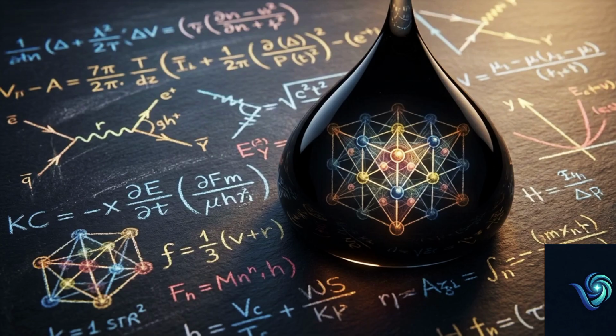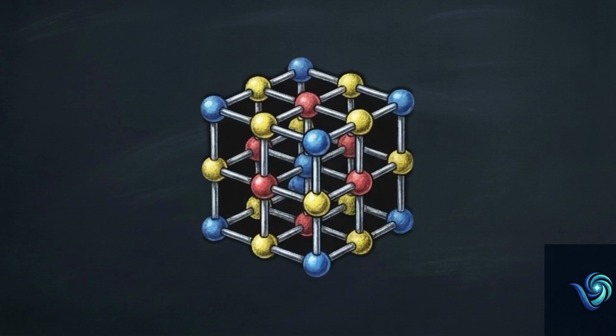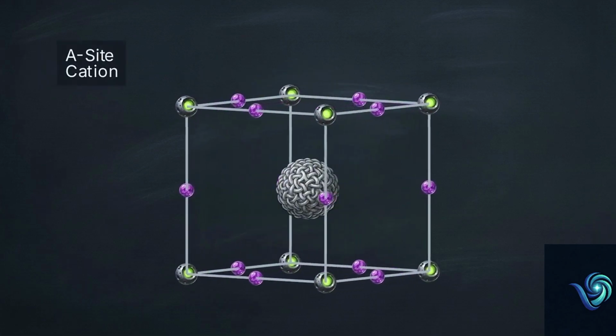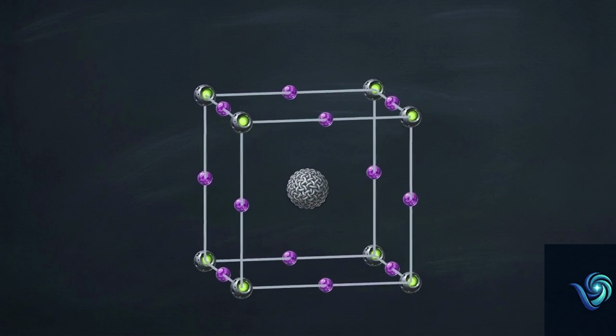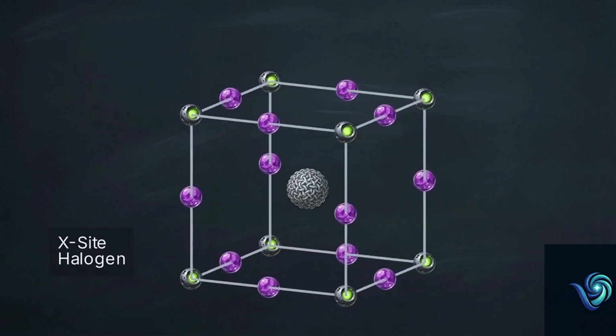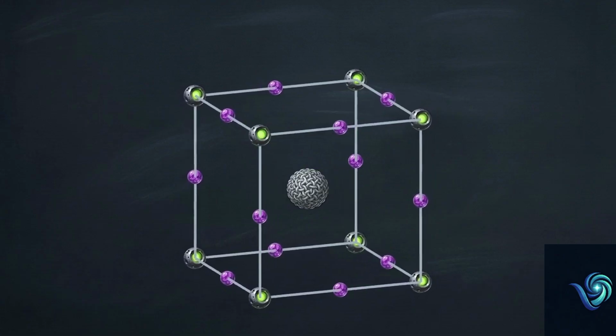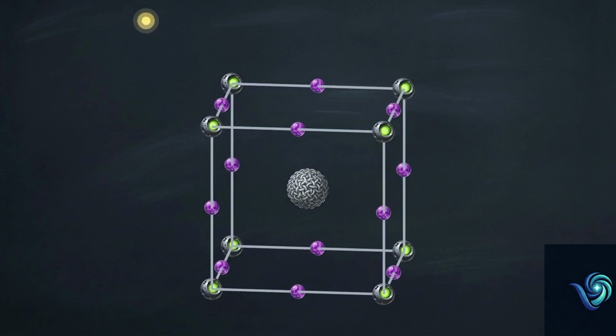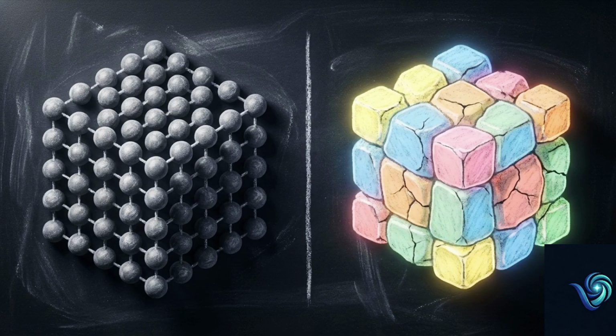To understand how printed liquid rivals refined crystal, we must look at the sub-nanometer scale. This is a 3D model of the perovskite ABX3 crystal lattice. It consists of an organic or inorganic cation, labeled A, a metal cation, labeled B, and a halogen anion, labeled X. This structure possesses a uniquely low exciton binding energy. When the lattice absorbs a photon, it spontaneously generates an electron-hole pair that easily separates at room temperature and travels through the material. Silicon requires near-perfect crystalline purity to function. Perovskite exhibits defect tolerance, operating highly efficiently even when deposited as imperfect polycrystalline thin films.